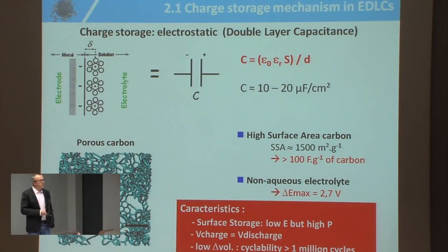But there is a price to pay, which is the cell voltage. In a pure dielectric, cell voltage is limited by the voltage breakdown of the dielectric. Here, this is the same. It's limited by the electrochemical stability window of the electrolyte. In water, you know that if you polarize beyond 1.2 volts, water is going to be oxidized into oxygen and reduced into hydrogen. If you replace water with an organic solvent, propylene carbonate, acetonitrile, then you can reach 2.5 volts for a single cell, and from 0 up to 2.5 volts, you just charge the supercap by ion adsorption onto the carbon. Okay?